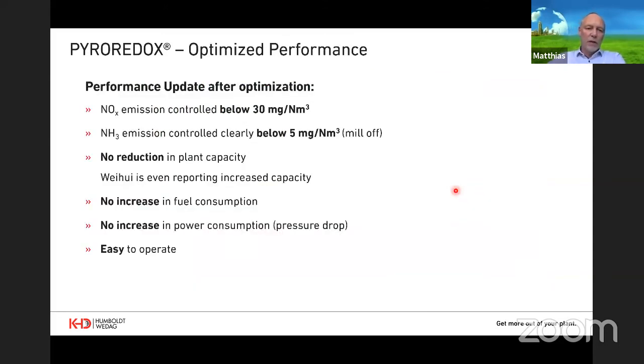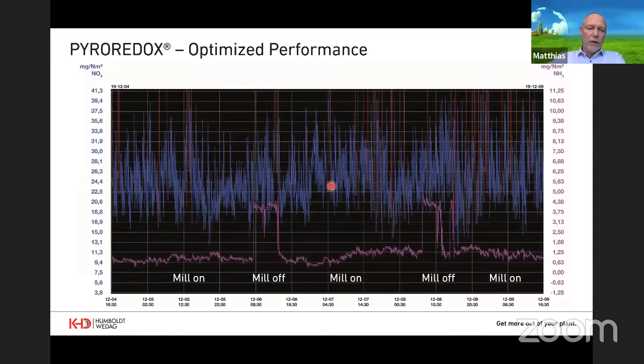We then optimized the plant, and I show you this picture here, which shows the NOx emission level in milligram per normal cubic meter as this blue curve. And we see also the ammonia injection in this magenta curve. And you see that we ended up with emission levels averaging around 26 milligram per normal cubic meter, with a very low ammonia injection in the range of 1 milligram per normal cubic meter. So this underlines the powerful performance of this. We speak of an inherent integral NOx reduction by the Pyro Redox system.